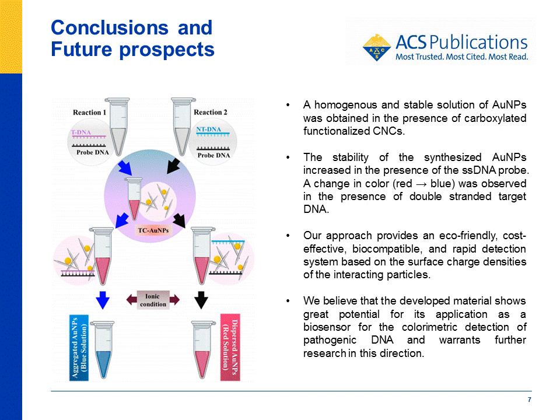We conclude that a homogeneous and stable solution of AuNPs was obtained in the presence of carboxylate functionalized CNCs. The stability of the synthesized AuNPs increased in the presence of single-stranded DNA probe. A change in color from red to blue was observed in the presence of double-stranded target DNA. Our approach provides an eco-friendly, cost-effective, biocompatible, and rapid detection system based on the surface charge densities of the interacting particles. And we believe that the developed material shows great potential for its application as a biosensor for the colorimetric detection of pathogenic DNA and warrants further research in this direction.